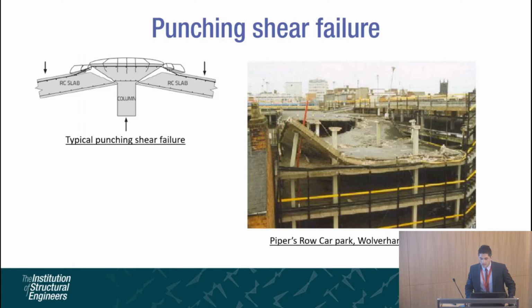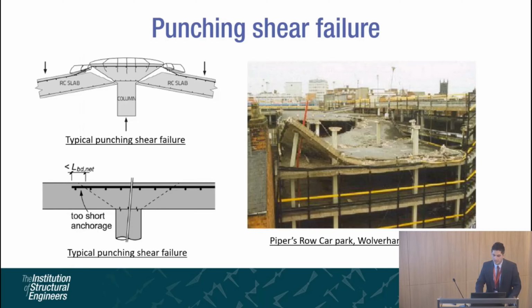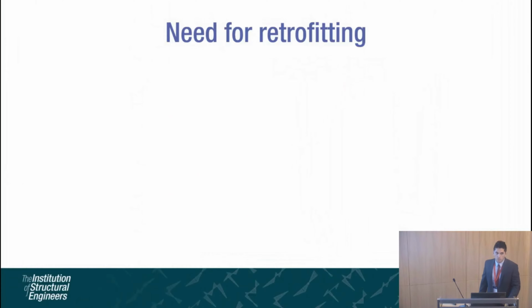entire floor. In the recent past, tragic examples of such cases have increased the general awareness, and research has been done to address this issue. With this specific case, the main issue was shorter anchorages in combination with corrosion of the flexural reinforcement, which led to failure of this connection, the slab. The number of aging structures are increasing. There are similar structures to Piper Row car park which are in need of retrofitting.